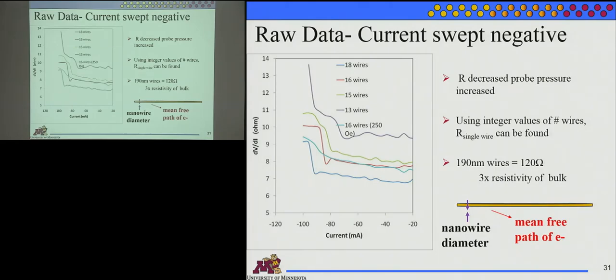And our nanowire, which looks like this, is 190 nanometers. So that's kind of unsettling, because that's about bulk resistivity. And most people that either measure or calculate resistance in copper, because most of it was copper and then there was a little tri-layer in the middle, would say, well, the mean free path of an electron is 40 nanometers.